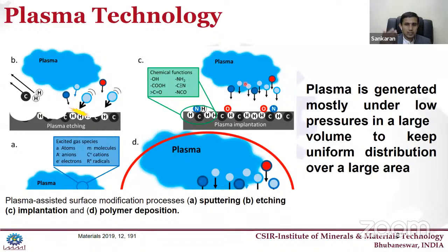Particular ions can be implanted inside your material, or you can do a surface treatment, at a surface level of maybe 3 to 5 nanometers. Plasma cleaning can also be done, in which you change the surface of your material from hydrophobic to hydrophilic, or remove unwanted material from your surfaces. We can do this with plasma technology, so you don't need any kind of chemicals here.